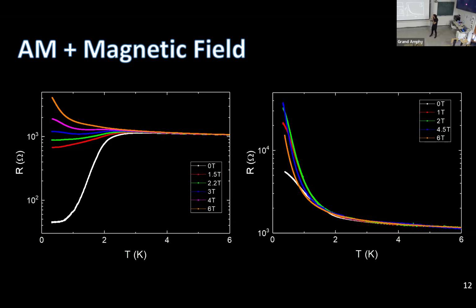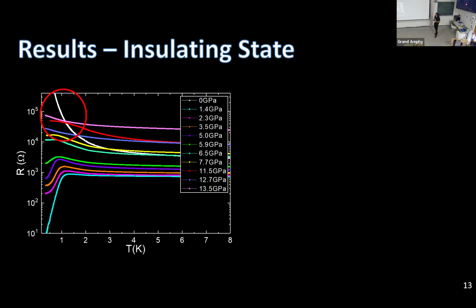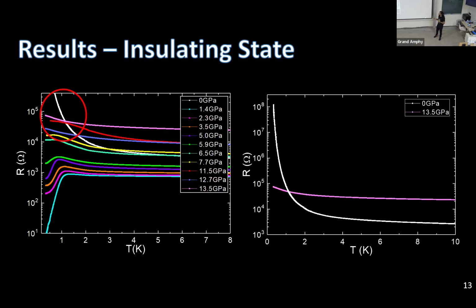One more thing that we saw is when we take a look at our insulating side and we compare the most insulating sample, the most pressurized sample, and the ambient one. Take a look in a zoomed picture on both of them. And even before I analyze anything, we can see that the two of them are far from one another. The pressurized insulating state seems to be much weaker, even though its resistance in the normal state, at higher temperature, is an order of magnitude higher than the resistance at ambient pressure.